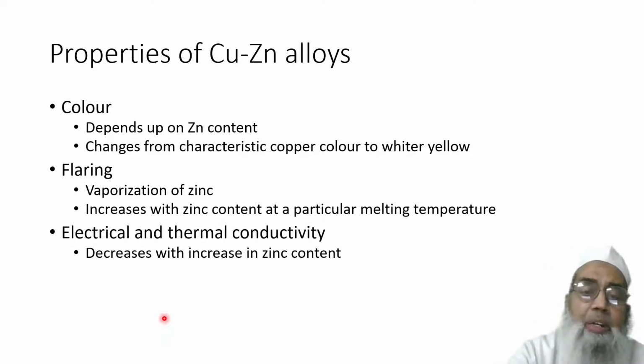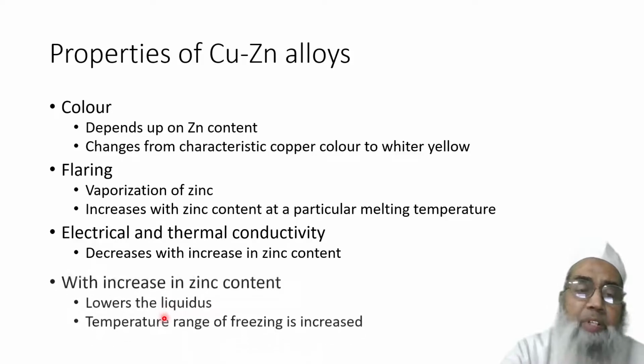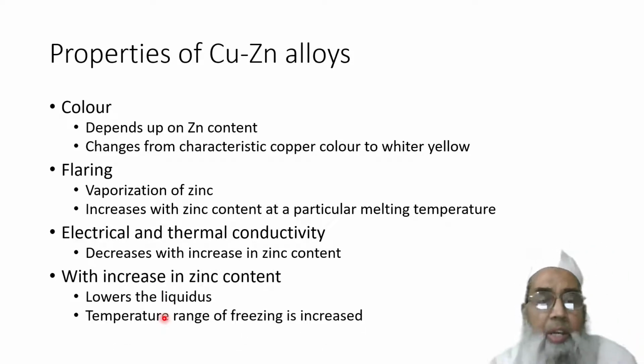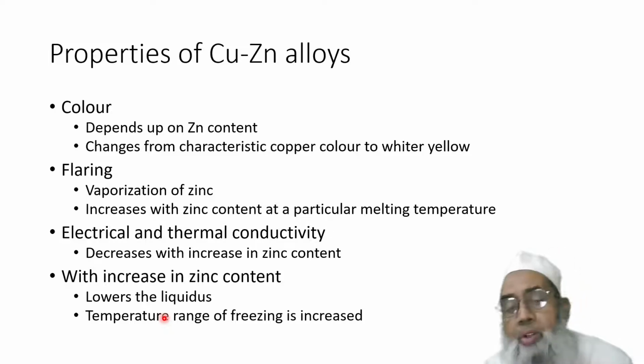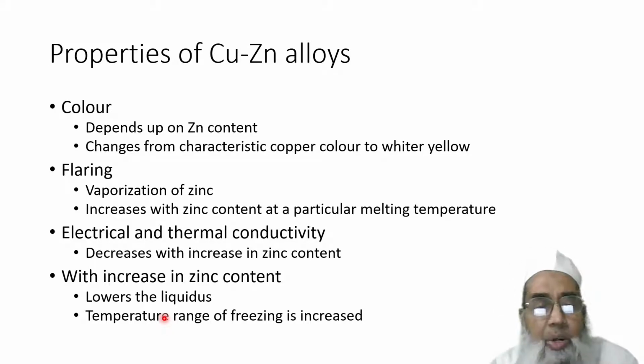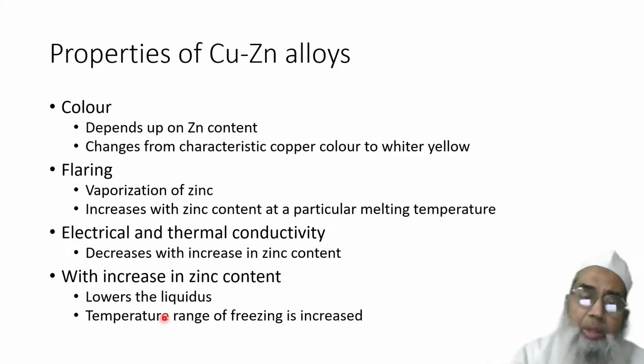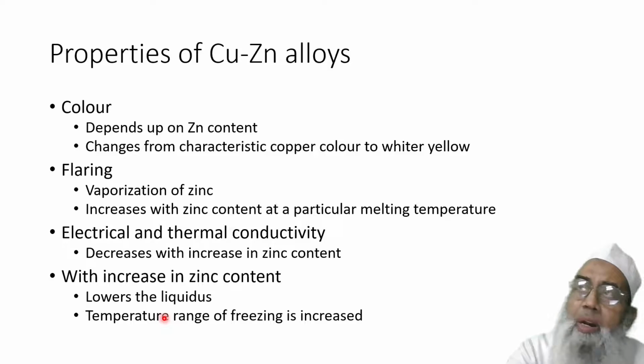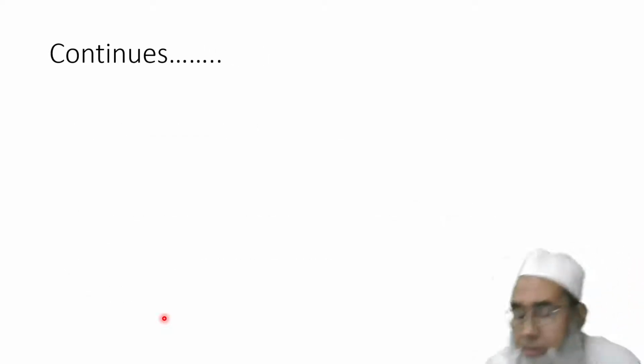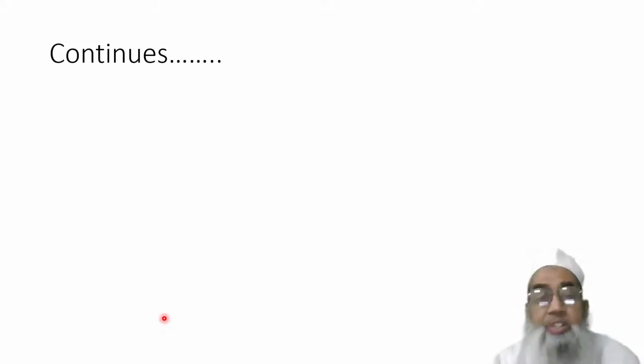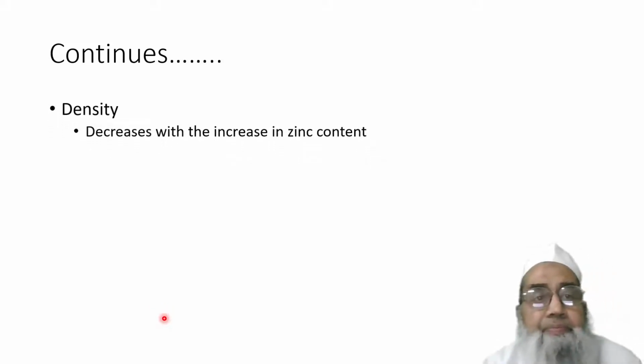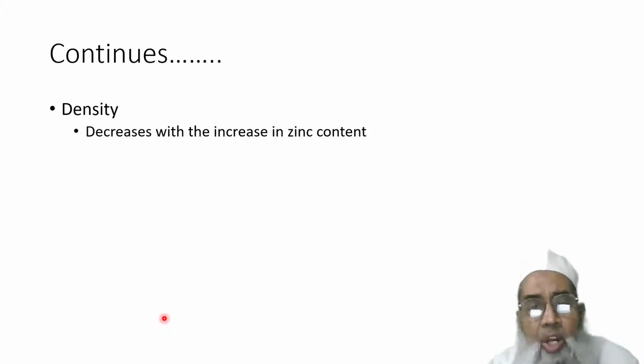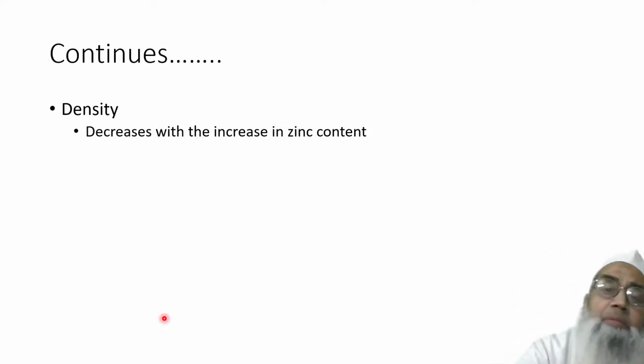Therefore, depending upon the requirement, we have to take into account how much zinc is required. With the zinc content, as we look into the phase diagram, the liquidus is lowered, and the temperature range of freezing increases with increase in zinc content, and therefore this will promote dendritic formation of the crystals. Moreover, the density of the alloy will decrease with the increase in zinc content.